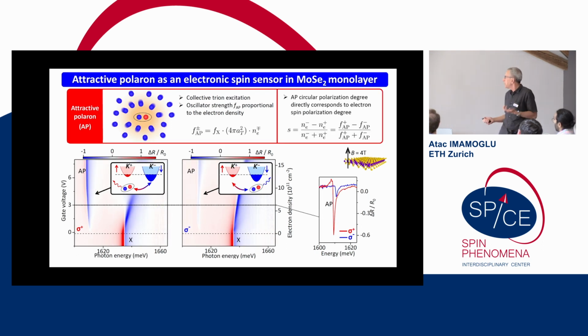So this is an extreme scenario. What is more interesting is for finite or even small fields, where we will have some attractive polaron intensity in the other valley, that is, some electron density. Now we can look at the ratio of these strengths to determine the magnetization of the system in the presence of magnetic field, or in principle also in the absence of magnetic field. In this way, we have a very sensitive and direct measurement of the magnetization of electrons.